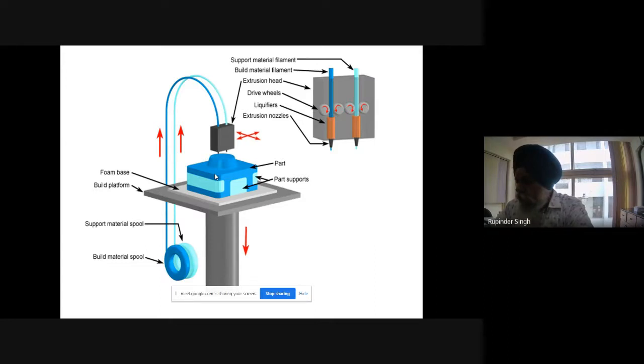Once this support is added, we put this particular part into the ultrasonic cleaning chamber, where at around 65 degrees Celsius at 30 kilohertz frequency, we immerse this component in water, and the whole water soluble support is dissolved, and finally we get a finished component. This is the most commonly used technique, right?